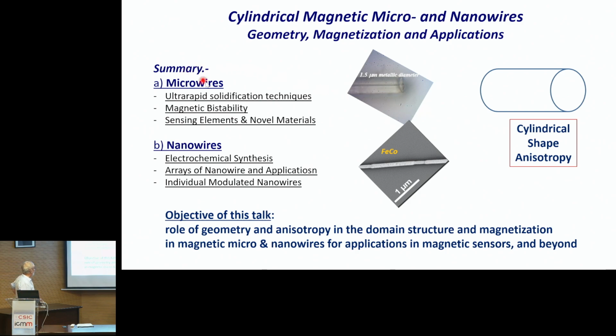I will be talking about two families of magnetic wires, micro and nanowires, depending on the diameter of these wires. Microwires have roughly from 10 to 100 microns in diameter, and nanowires from 20 to 200 nanometers, roughly. The objective of the talk is to underline the role played by the cylindrical geometry in the magnetic properties, domain structure, magnetization reversal process, and particularly on the applications. I will emphasize particularly the different applications that we have developed with micro and nanowires.